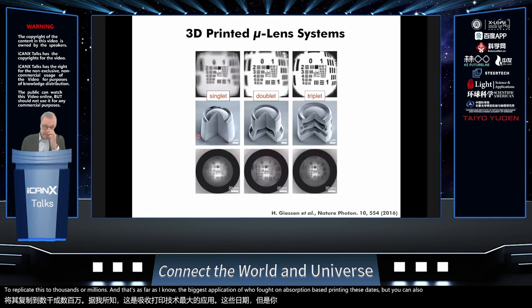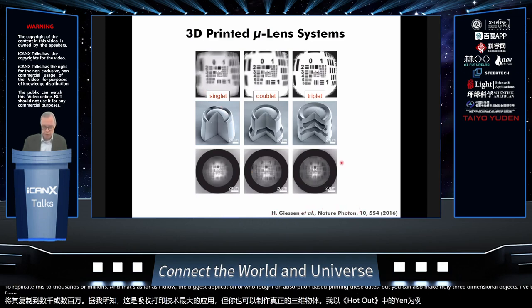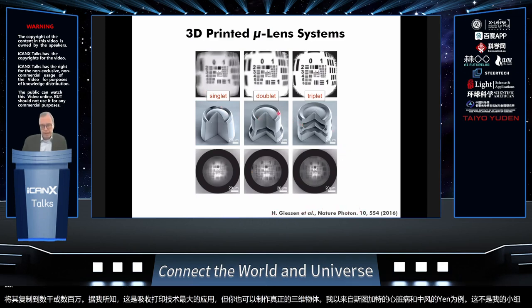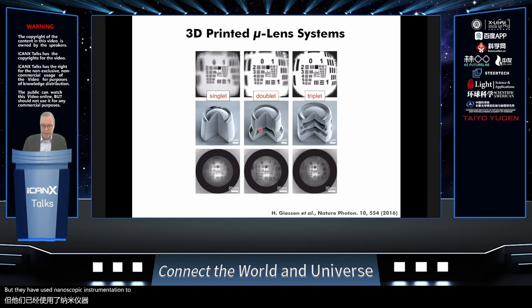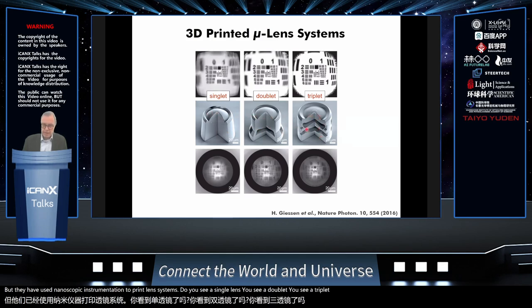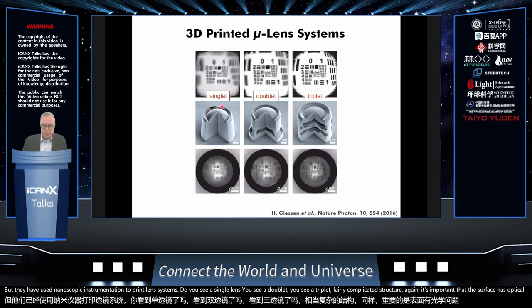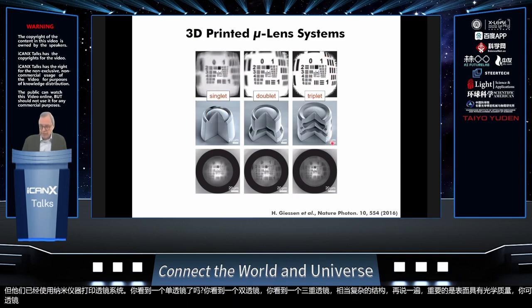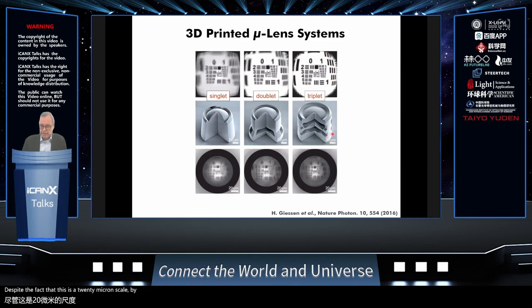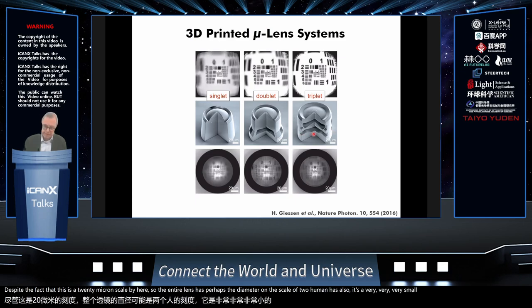But you can also make truly three-dimensional objects. I've taken here an example from Harald Giessen's group from Stuttgart. This is not my group, but they have used Nanoscribe instrumentation to print lens systems. Here you see a single lens, a doublet, and a triplet, fairly complicated structures. Again, it's important that the surface has optical quality, and you can see that you can use these lenses. They have good imaging quality, despite the fact that this is a 20 micron scale bar here. So the entire lens has perhaps a diameter on the scale of two human hairs or so. It's a very, very small lens that has been printed.